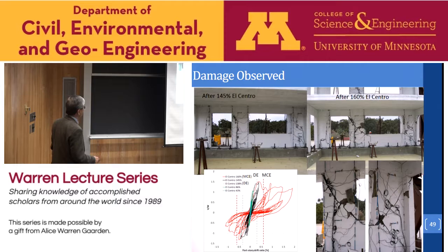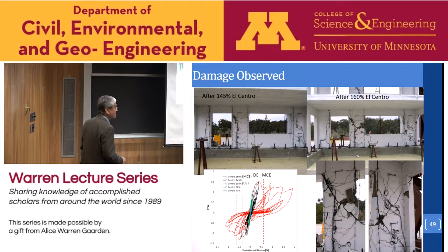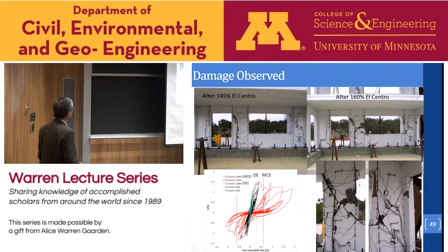The structure drifted close to 2%. This is quite amazing for a shear-dominated wall. This can be attributed to the system-level behavior of the masonry.